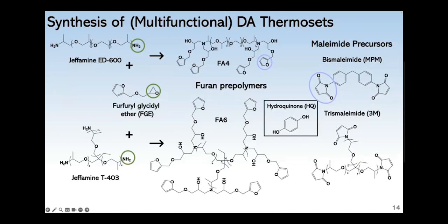So with that introduction in mind, I'll explain to you how we synthesized our own Diels-Alder thermosets. We also use polyetheramines and then this furfuryl glycidyl ether with the epoxy group to do the epoxy-amine reaction. And that created a 4-arm furan and a 6-arm furan. And we also use Jeffamine T403 to synthesize this flexible tris-maleimide compound, which is in contrast to the more common bismaleimide compound, which if you just look at the chemical structure, you can imagine it's not going to have a lot of flexibility in that backbone with the phenyl rings.